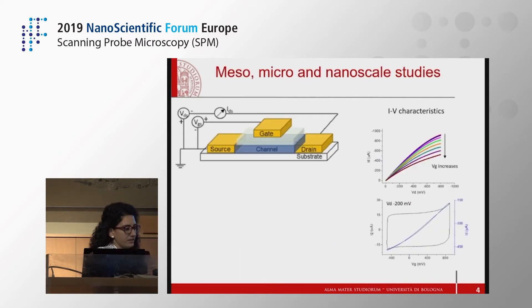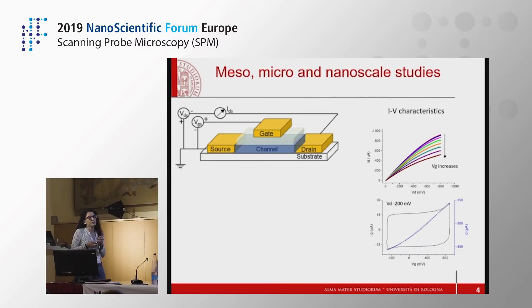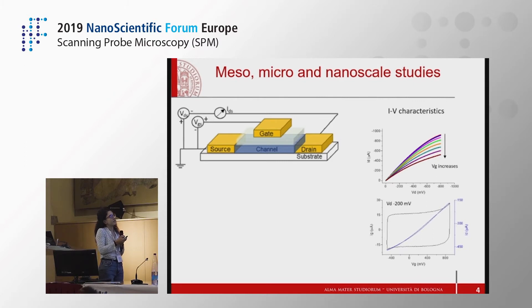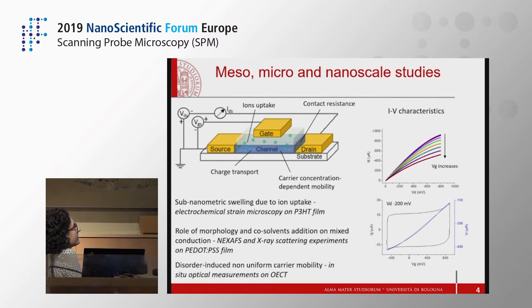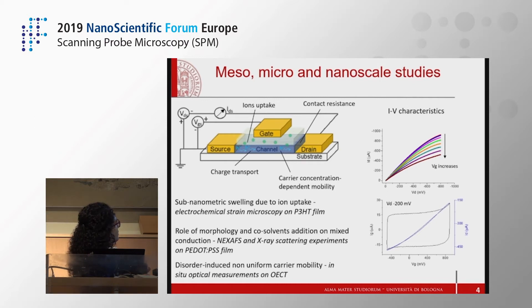These devices belong to a cross-disciplinary domain, and to date the physical and electrochemical events that rule their operation are still not fully understood. Generally, device performance is evaluated by recording IV characteristics — a macroscopic evaluation — which loses information about the microscale. In contrast, studies at the meso, micro, and nanoscale have highlighted sub-nanometric swelling due to ion uptake and the role of morphology and disorder-induced effects on mixed conduction.